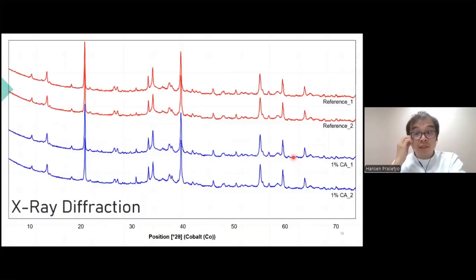But I also did X-ray diffraction to see whether the constituents of the solid phase differ from each other. For the reference, I had 2 reference samples, and then 2 samples with 1% of CA added. And as far as my eyes can see, they are the same.